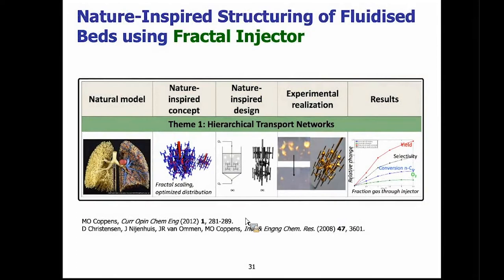And so what I've done now is to go through this approach. We take inspiration from nature, not just imitating the lung or the tree immediately, but deriving the concept of the fractal architecture, but also the concept of scaling and keeping that smallest scale constant so that you can do studies at a small scale with a small distributor and then just change the number of generations when you scale up to a large one. So you have to build prototypes, which we could do. Years ago, we did this with plastic tubes and then with steel tubes, and you weld them together. It's quite difficult.